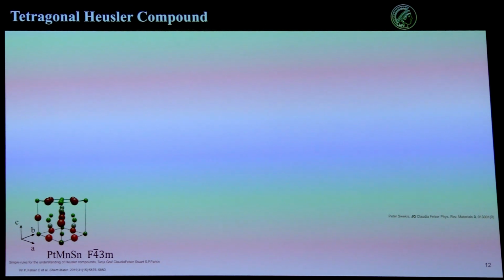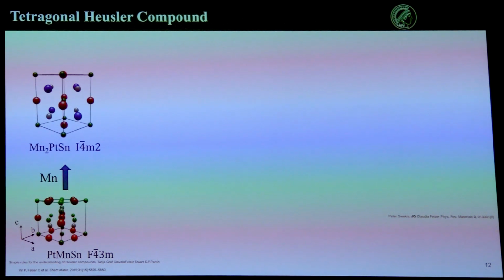And as you begin to add more manganese, you have a problem here. What happens is you start putting in more density of states, and you put them in right at the Fermi energy. And this becomes unstable for the system. And this actually causes what's called a Jahn-Teller distortion. So what happens is the system becomes tetragonal to push all your d states down. And so this is the manganese 2 platinum tin, which is what we'll talk about today.